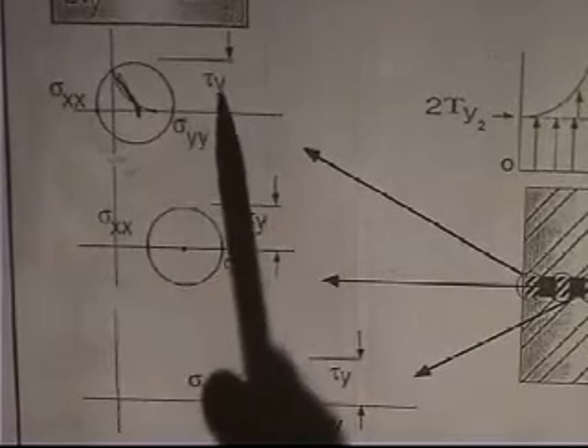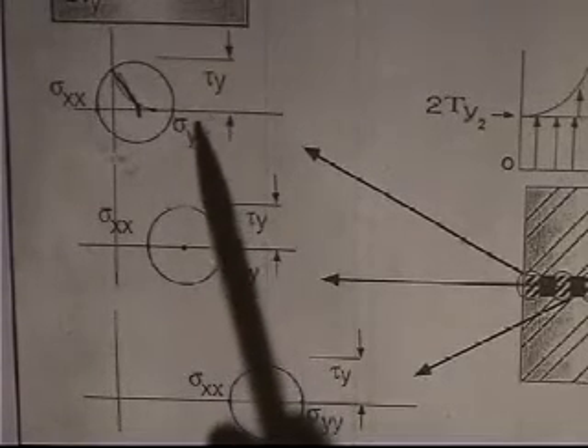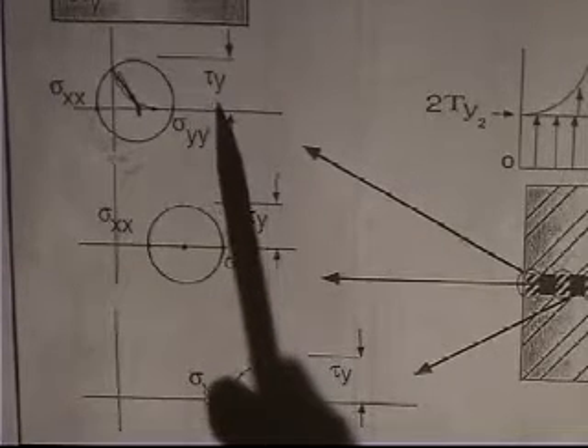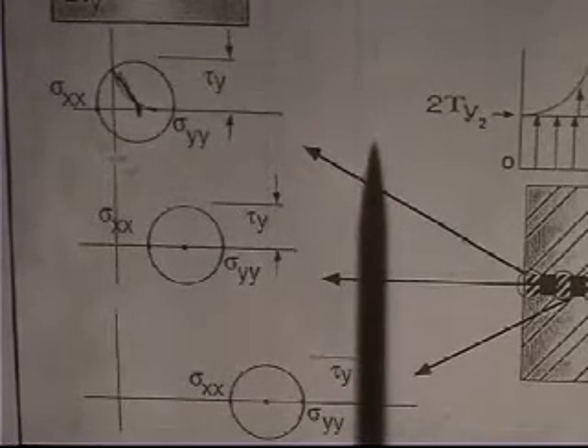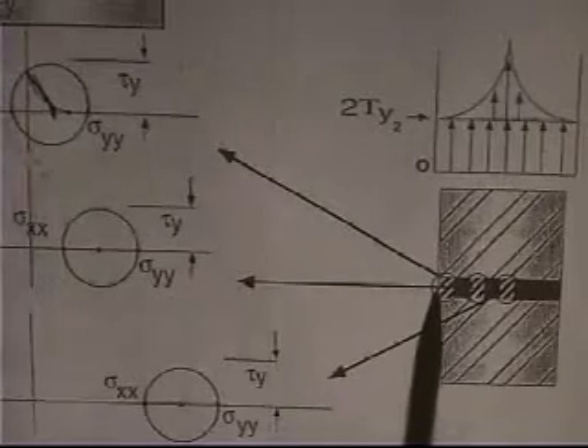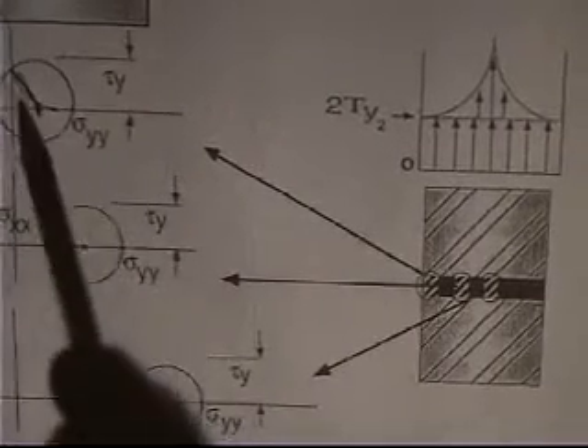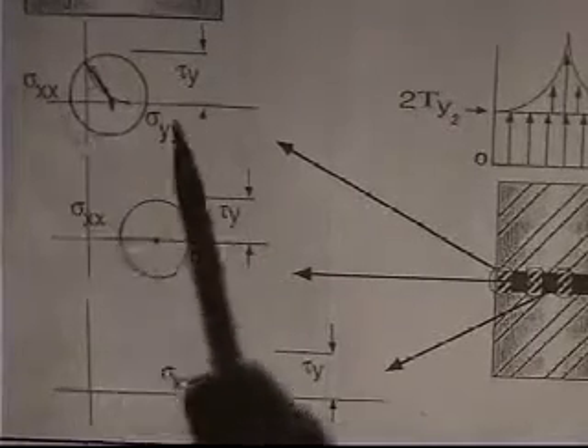But basically, there is some shear stress of the material, tau y. That's the shear stress of the braze alloy. If we were talking about the silver joints, that's the shear stress of the silver. If the silver has a tensile strength of 10,000 psi, the shear stress is about 5,000 psi. And it's not going to be any greater than that, because how can it get stronger? The silver doesn't get any stronger. And so right here on the edge where the material is not constrained, that silver will start to yield at 5,000 psi shear stress. And this is what the Mohr circle looks like. This would be Poisson's ratio times sigma yy, and that's just sigma x. Sigma xx is Poisson's ratio times sigma yy. And there's the Mohr circle.